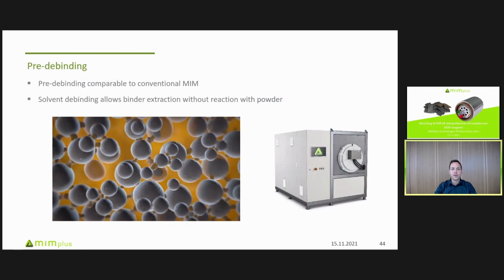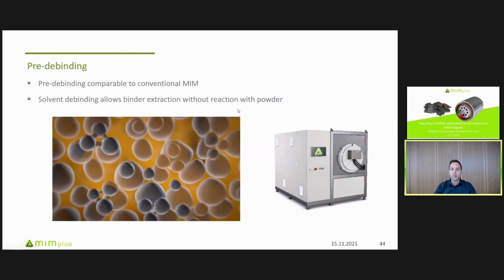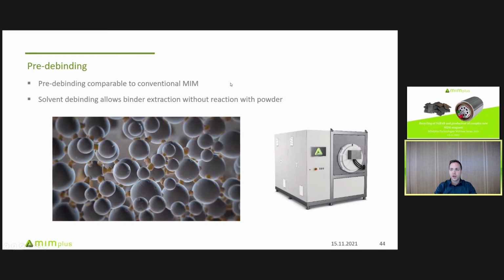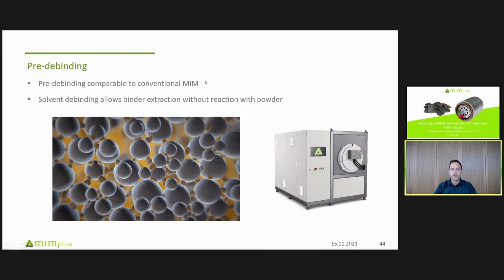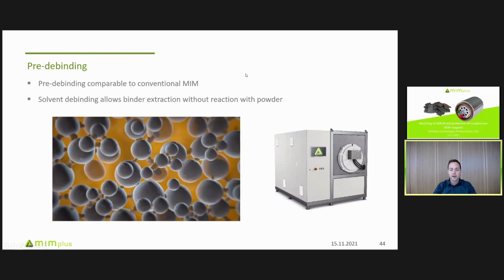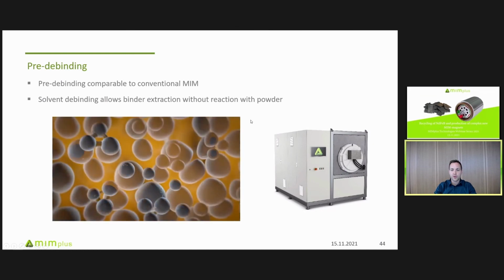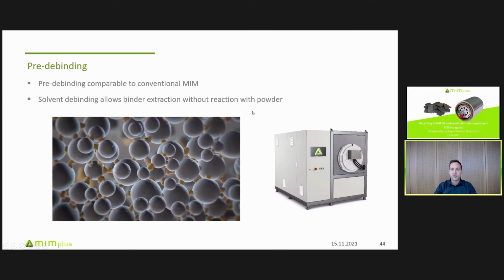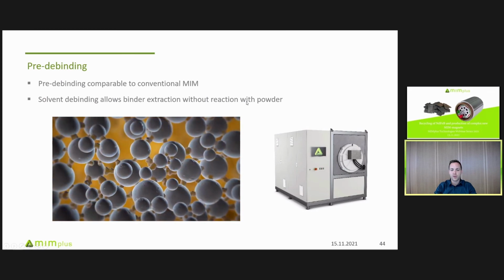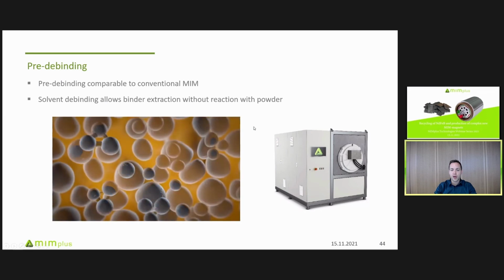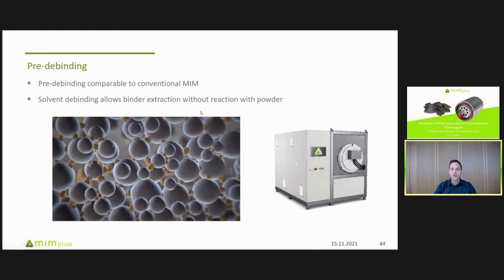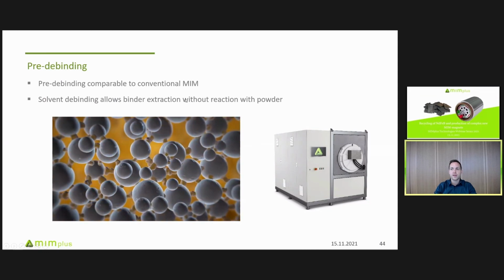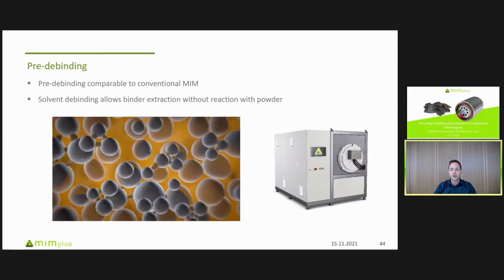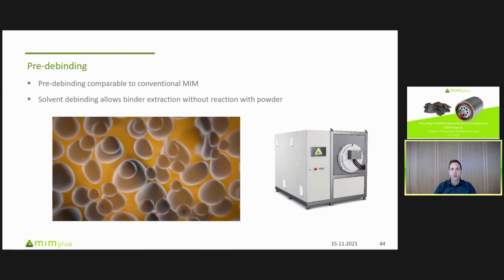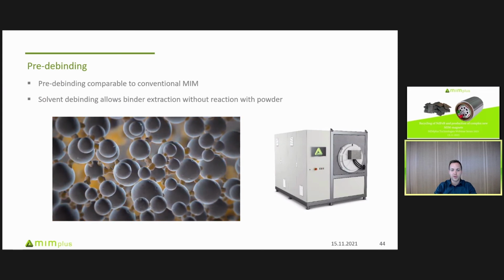After production of the green part, the so-called pre-debinding follows, which is well comparable to conventional metal injection molding. You can use, for example, organic solvents that allow extraction of the binder without reaction with the powder. The extraction of the binder means here removing two-thirds of the organic binder in the feedstock. And then what will be left, as shown here in the capillary bridges between the particles, is the so-called backbone binder, which keeps the debinded parts stable so they can be transferred easily to the next step, the thermal debinding and sintering, without letting the parts fall apart.